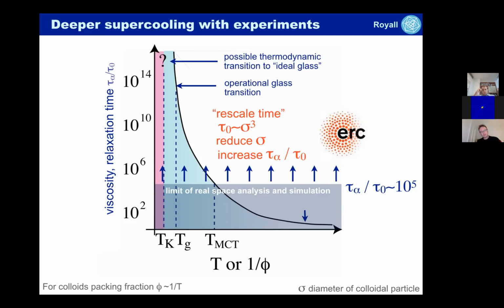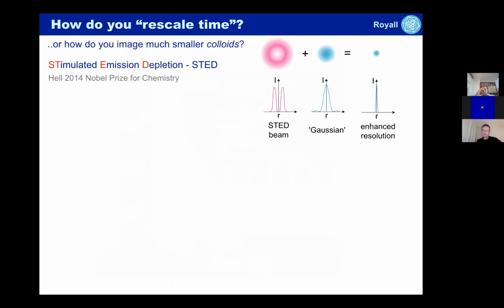So we can image for 1 day. Suddenly, we're now imaging for 1,000 days if we can obtain data for smaller particles. We do this using a microscopy technique called stimulated emission depletion. This is one of a number of techniques which have come out which essentially beat the diffraction limit and enable us to image smaller particles than diffraction would otherwise allow.